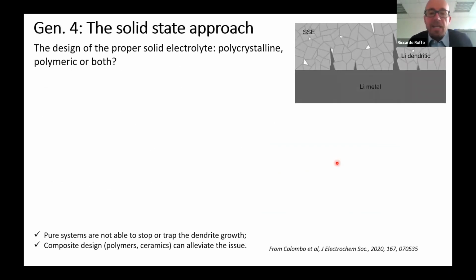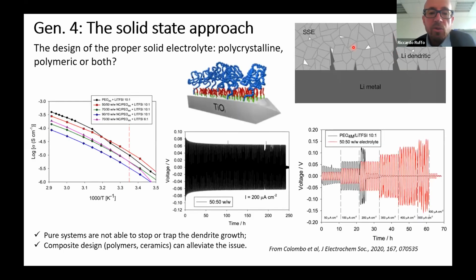However, one of the main subjects for the use of metallic lithium is the solid state approach. The idea is to have a material which is able to block the growth of the dendrite. Unfortunately, dendrites are able to penetrate inside the grain boundaries of my solid material. I'm not going to give you too much detail about that because I guess that the next presentation will be all about that. So I give to Jijeesh the stage, and he will present all these results. He's much more expert than me.